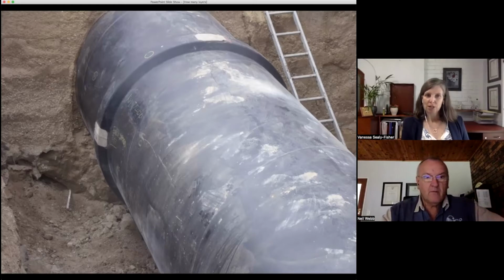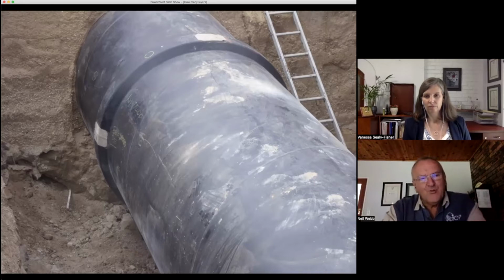One of the challenges that I see with that is that although it's holding onto the pipe, it doesn't have any corrosion inhibition in and of itself. That is correct, because as I said, the polyethylene itself is very inert and it doesn't interact with the moisture and oxygen. There's no, what I like to call glue factor. There's nothing that makes it stick to the underlying steel. It's just this mechanical interlocking. And I'm not saying that it doesn't work. It does work, but it does have its own shortcomings.